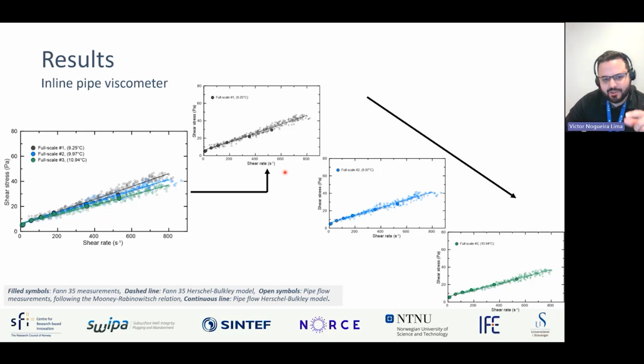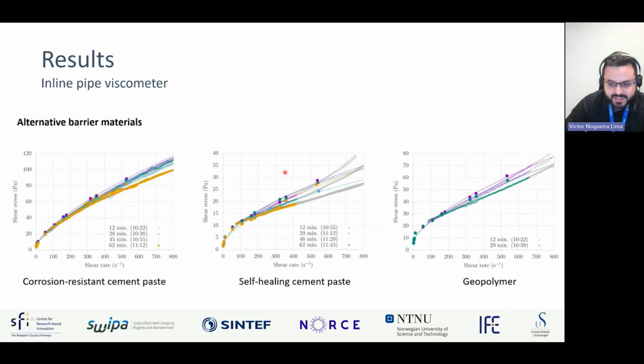However, until we reached this stage where we could attach the pipe viscometer to a full-scale batch mixer, we had a very long way where we tested different polymeric fluids, water, and different scales, starting from very small scales. We increased the scales, we tested different cement pastes, and we also tested different alternative barrier materials. By that time, we wanted to make sure that the pipe viscometer could do the readings and have very good agreement between a conventional way of doing the measurements and the new way, the inline way of doing the measurements. And this could match without any impact or effect caused by the type of material that we used.